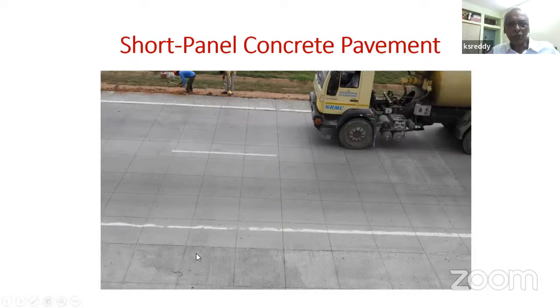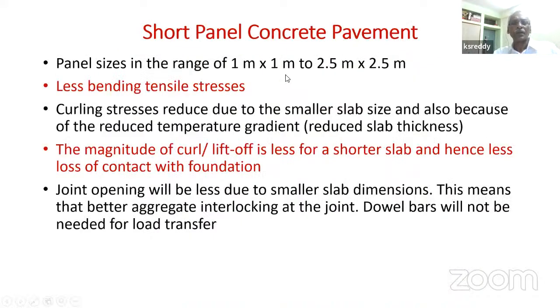And if the cracks develop below these grooves that you cut, that means the joints are activated, then you get panels of this size. Provided the joints activate, there is a crack that is going to form below every groove that you cut. So this is the individual panel size, and they are interlocked with the adjacent blocks. If you place a load somewhere here, maybe all these blocks will share the load because of the interlocking among those blocks. Typical panel sizes would be 1 meter by 1 meter to 2.5 meter by 2.5 meter.